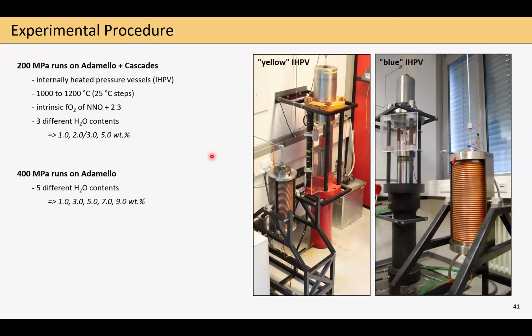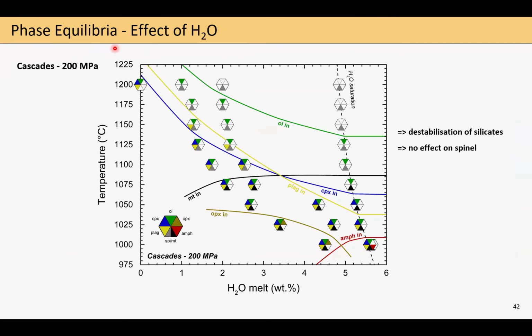So let's have a look now at some of my data. But first, I want to show you the effect of water on phase equilibria, here first for the Cascades basalt at 200 megapascal, where in this temperature-meltwater phase diagram, each hexagon corresponds to an experiment I did, where the smaller colored triangles indicate if the corresponding mineral phase was stable or not at those conditions. So colored means stable. And the meltwater contents were established either by Raman spectroscopy, or if this data is not yet available, we're currently in the process of getting them measured, calculated by mass balance.